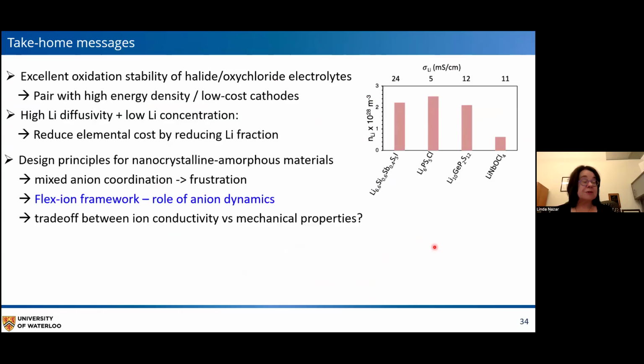So then, take-home messages. Hope I've convinced you that we achieve good oxidation stability of both the halide and the oxyhalide electrolytes, which allow us to pair these with high energy density, low-cost cathodes with no coating on the surface. In particular, many of these materials have a low lithium fraction, which makes them appealing because one can reduce elemental cost in this fashion. And this just compares carrier concentration in some well-known solid electrolytes, such as LGPS, that all have similar conductivities with the low concentration in the lithium niobium oxychloride.